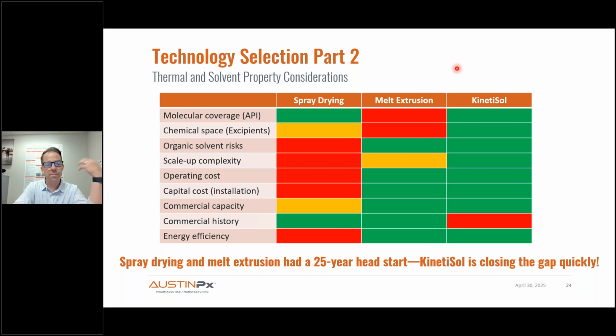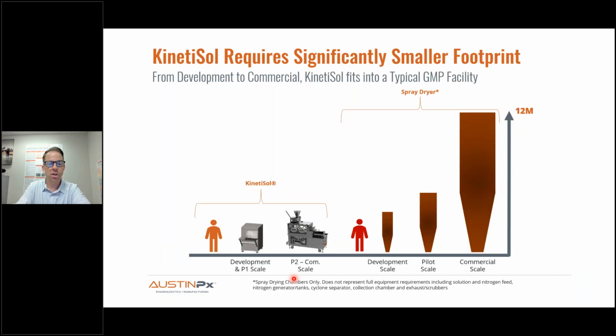So, melt extrusion, the biggest issue, molecular coverage is pretty poor, as I've already talked about, and the design space for formulation is pretty limited. So we look at the KinetiSol, again, it's coming up green in all these categories but one, and that's the commercial history. So the take home at the end of the day for this is that spray drying and melt extrusion had a 25-year head start. If we were all born on the same day, KinetiSol would be the go-to ASD technology within the industry, but we're behind, but we're quickly catching up, as I'm about to show.